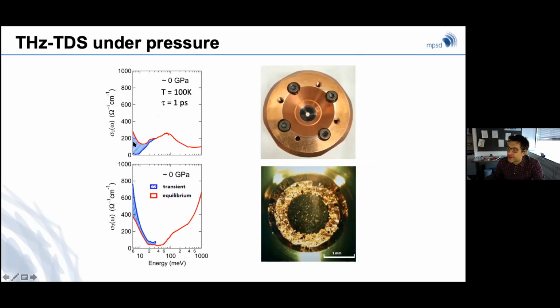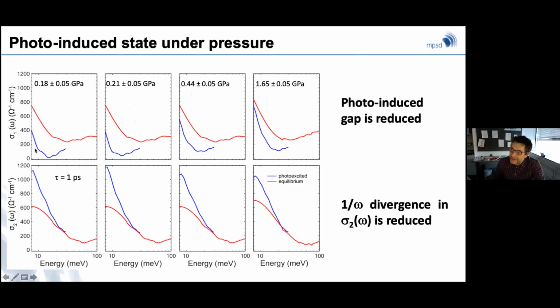And now she redid the experiment applying pressure, and you should watch the divergence of sigma 2 and the opening of the gap as the base pressure is walked from 0 gigapascal all the way to several gigapascal. As you can see, already at 200 megapascal, the gap fills in and sigma 2 is not as exciting as it used to be. At each one of these pressures, we calibrated the metallic state independently. Already at half a gigapascal, you can see the gap basically gone and sigma 2 starting to peak, indicative of a scattering rate that is walking in from being very low to being much larger. So this light-induced state gets worse with pressure, consistent with an equilibrium superconductor rather than a metal, okay?